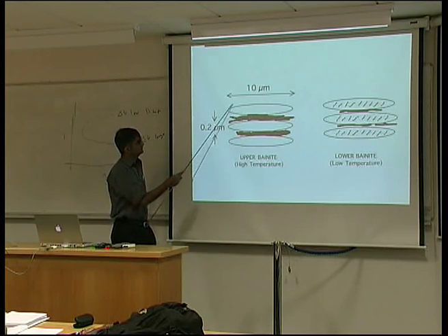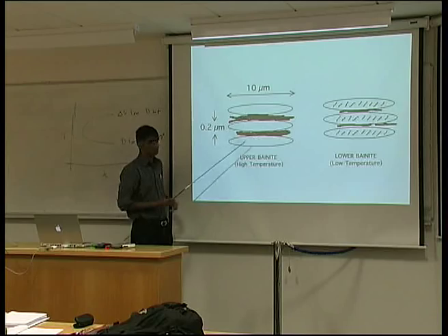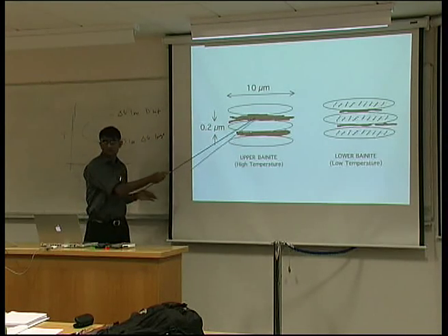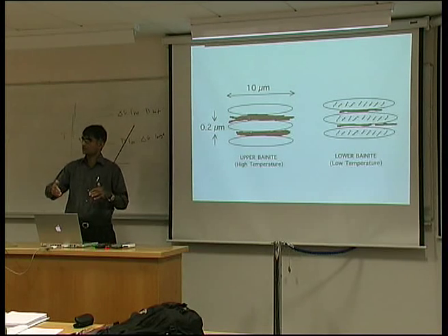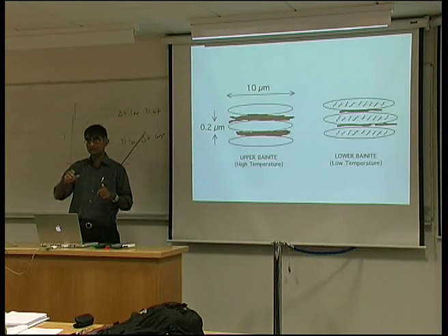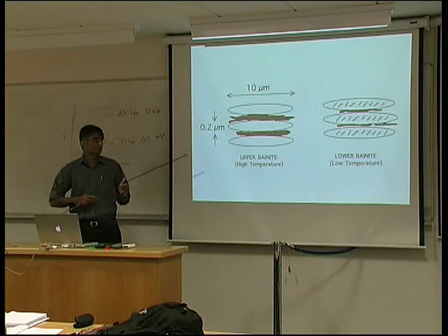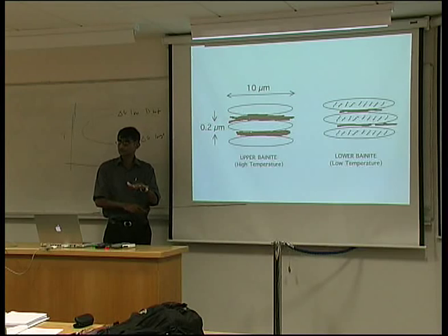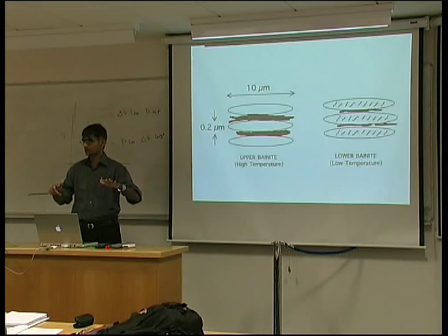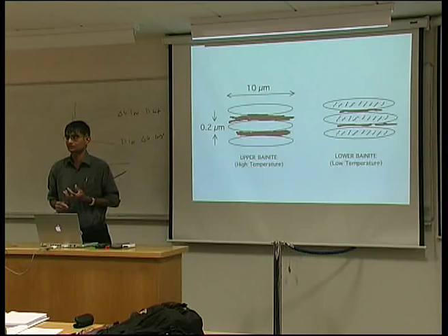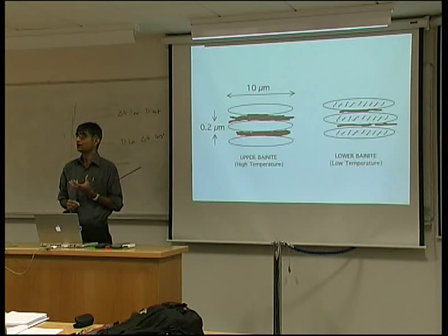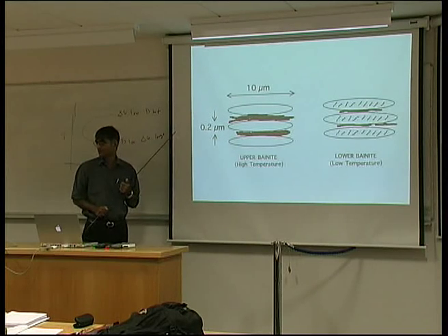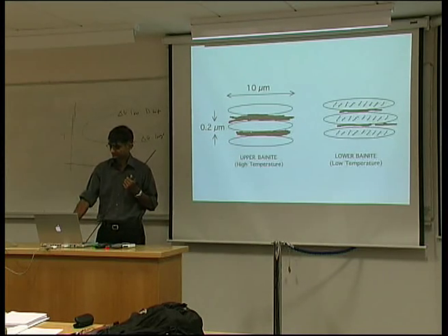But supposing I look at this in an optical microscope, then there are lots and lots of interfaces in this region, and all those interfaces are etched when you chemically attack your sample. So this region will appear dark. And when I show you an optical micrograph, you'll see that the bainite etches dark. So you can use information like that to deduce that you do have bainite. But you cannot resolve the individual features without using transmission electron microscopy.